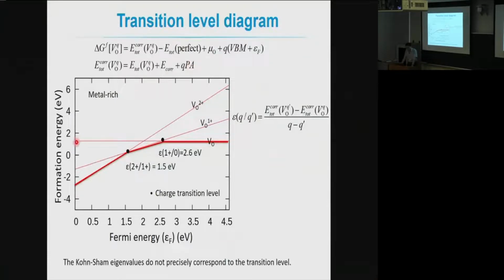Okay, so then we have this oxygen vacancy. When it is neutral, since Q is 0, it is not affected by the Fermi level position. The Fermi level here ranges from 0 to about 4.6 electron volts, which corresponds to the theoretical band gap of magnesium oxide. So the neutral oxygen vacancy is flat, constant throughout the Fermi level range.